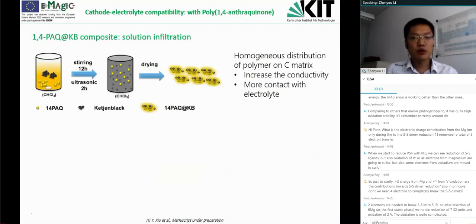Because we know that in principle the polymer material has a relatively low conductivity, and with the normal preparation method, we could only have very limited accessibility of this active material from the cathode. That's why here we have used a reprecipitate method, hoping to have homogeneous loading of the active material on a carbon matrix, which has a high surface area, so that we could have increased conductivity of the cathode and also have more contact with electrolyte. So we hope by this approach we could increase the capacity as well.